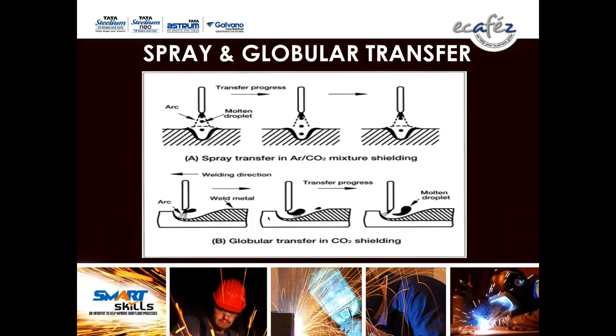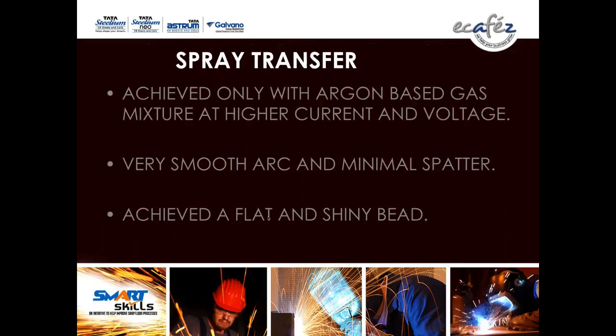Globular transfer in CO2 welding will give very bad quality weld. Spray transfer is achieved only with the argon-based mixture at higher current and voltage. True spray transfer will not be available by using CO2, only by using argon-CO2. Very smooth arc and minimal spatter.